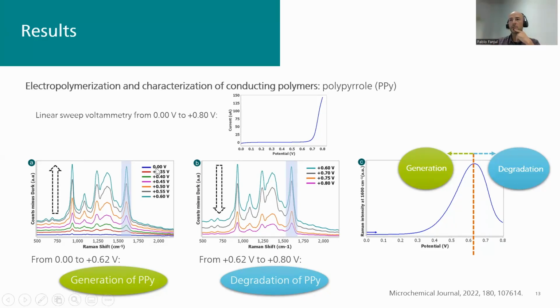So at the starting potential at 0 volts, we have this Raman spectra, but once we are going to higher potentials, we can start to see these specific Raman bands at specific Raman shifts that allow us to understand that the polypyrrole is being generated. And as well as we can follow the generation of the polypyrrole, also we can understand that at very specific potentials higher than +0.6, 0.7, 0.8 volts, we start to generate a degradation of the polypyrrole.